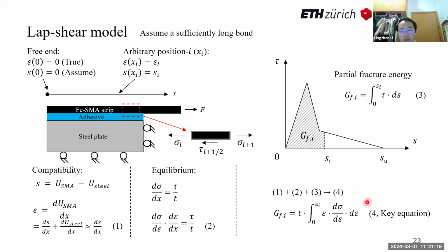I call it the key equation in my study. It is very elegant and useful because it links the fracture behavior in the bond line, the left-hand side, and the stress-strain behavior of the adherend strip, the right-hand side. So far, in this model, I didn't introduce any stress-strain behavior. This means such a model is very general. It can describe not only the behavior of shape memory alloy bonded joints, but also FRP bonded joints, etc.